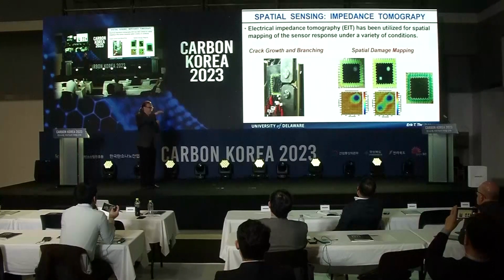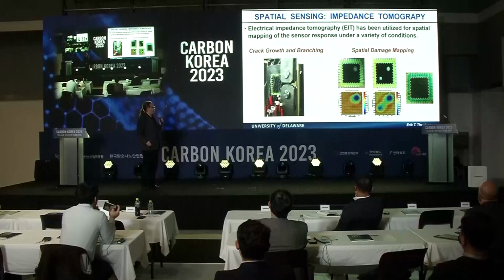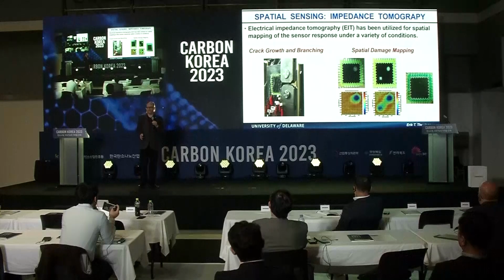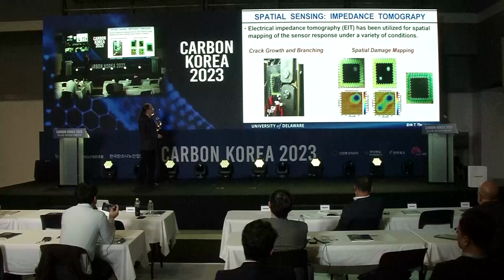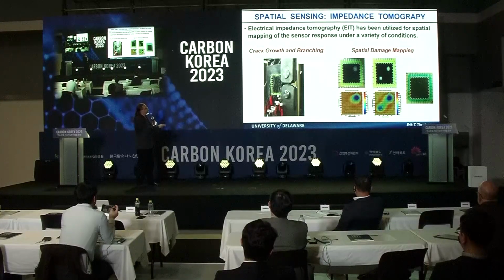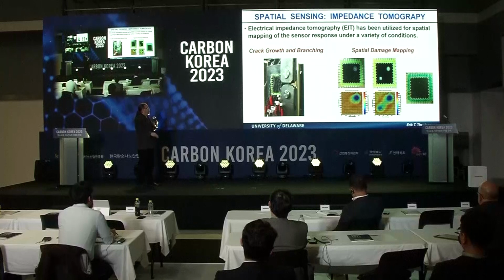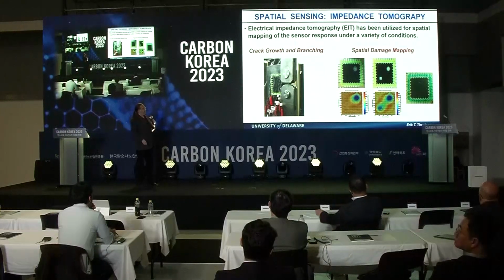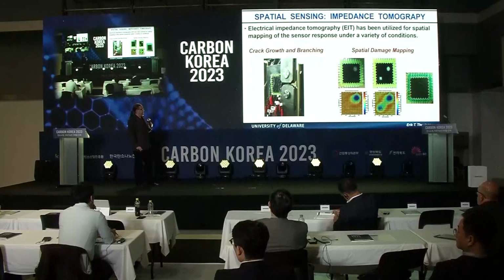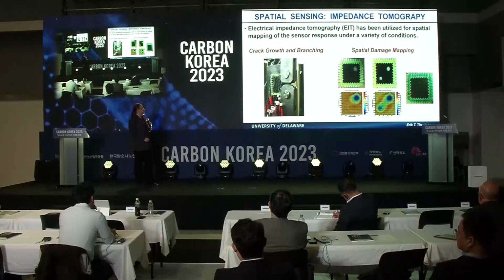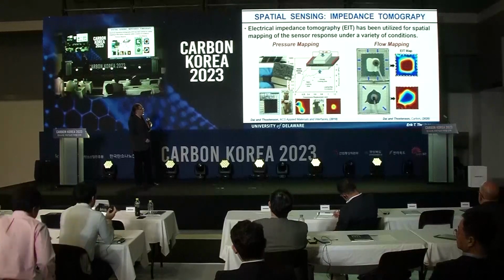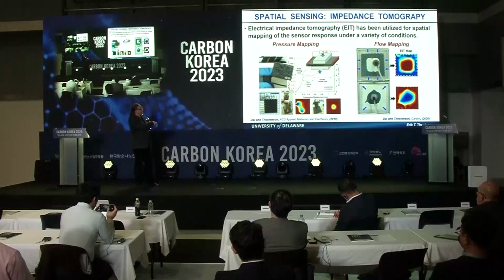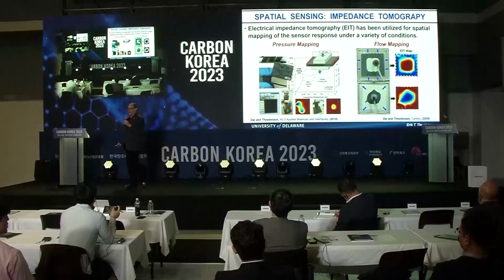Most recently, maybe about 7 years ago, we started looking at, well, where can we localize that damage? So what you see here on the left and right, those are where we're doing impedance tomography. So we're measuring conductivity around the boundary, and we solve the inverse problem using finite elements to get the conductivity distribution. And most recently, we're utilizing that for novel pressure sensors, what you see on the right, and also flow and cure in composites manufacturing.